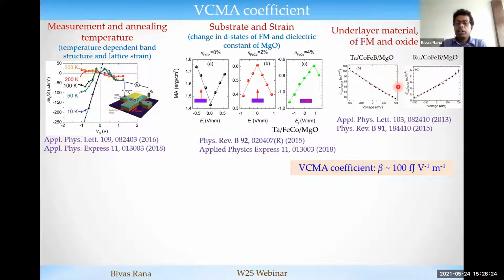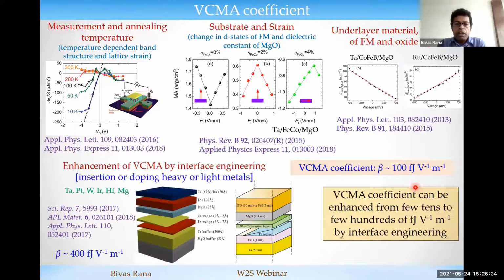So for a normal ferromagnet oxide layer, for example, cobalt iron boron MgO, this VCMA coefficient can be limited to a few tens of femtojoule per volt meter. But if you engineer the interface, for example, if you insert or dope heavy metal or light material at the interface, you can efficiently enhance this perpendicular voltage control magnetic anisotropy coefficient up to a few hundreds of femtojoule per volt meter. But for practical application, we need at least this beta value in picojoule per volt meter. So researchers are working on how to enhance this VCMA coefficient.